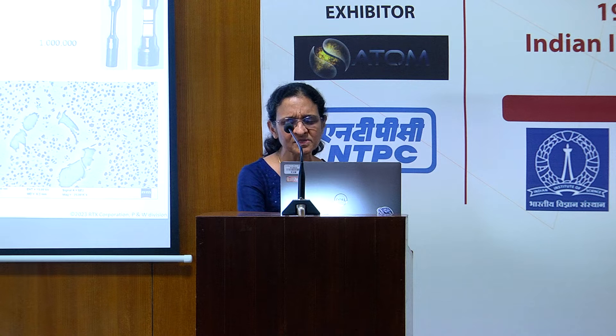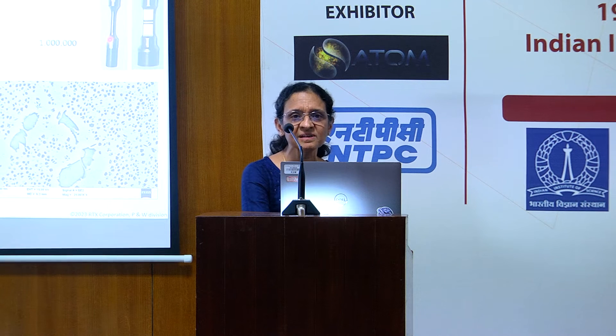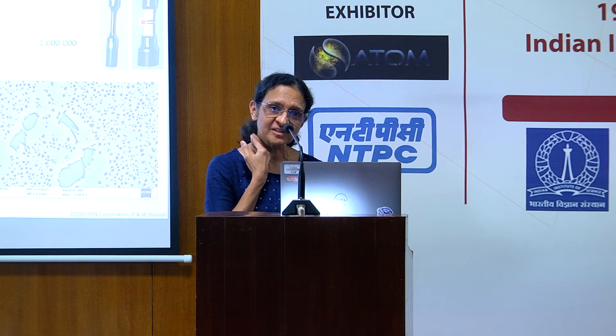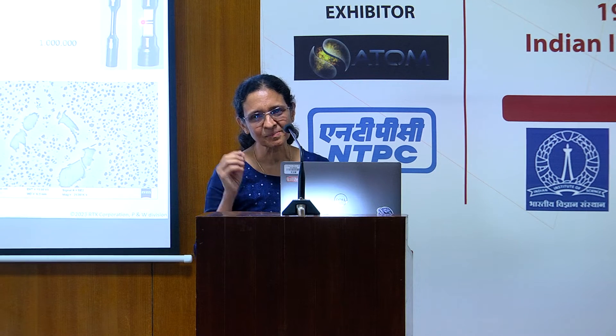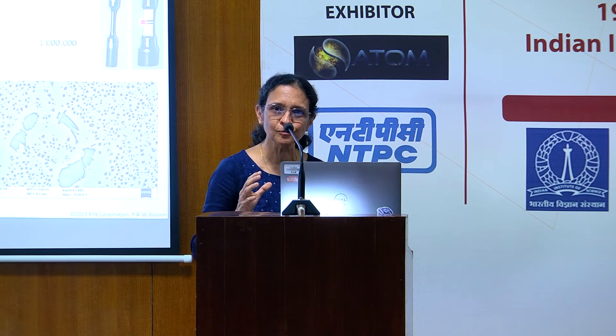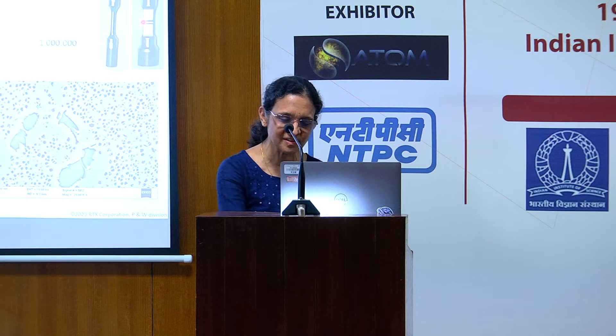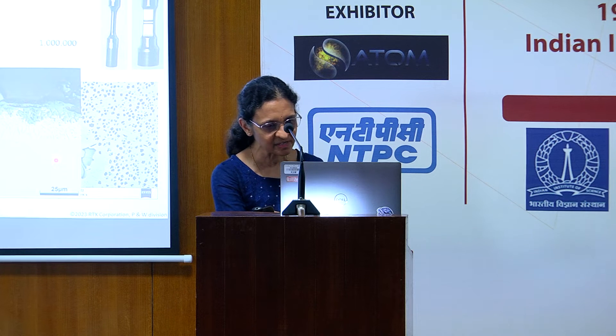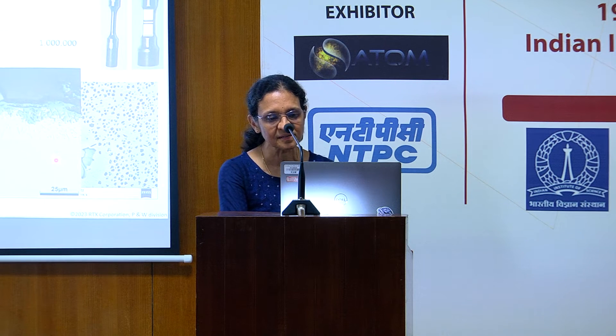What we did was take cylindrical ASTM samples and make notches of various dimensions. To get a notch without any manufacturing machining KT factor issues is very difficult. We can't do shot peening in a notch that small, and measuring residual stress is also a challenge. I'm giving you all the difficulties and what's the best you can do to adopt this and put a safety factor in the design. We launched a couple of detailed characterization studies at IISc — very recent work done in the last year.